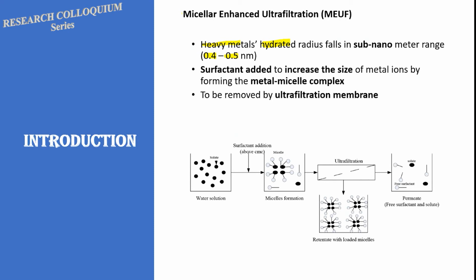So now we try to think, is it possible to use a membrane which has larger pore dimensions? Here we have a candidate, which is the ultrafiltration membrane. In comparison with nanofiltration, ultrafiltration has larger pores. But the problem is that when the pore is larger, these heavy metals are too small already, so they penetrate across the ultrafiltration. Eventually, we are not able to retain any of the heavy metals if we use ultrafiltration.